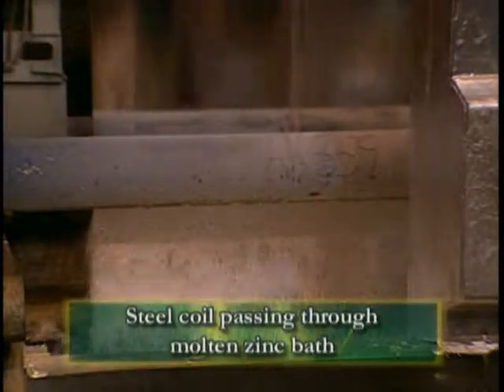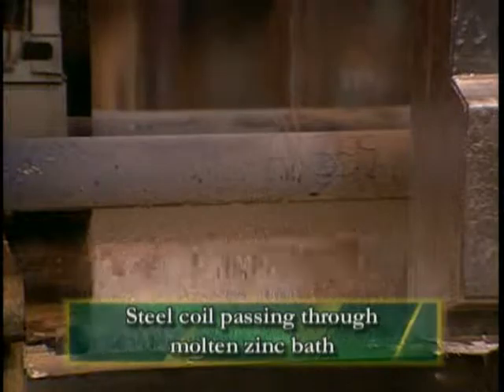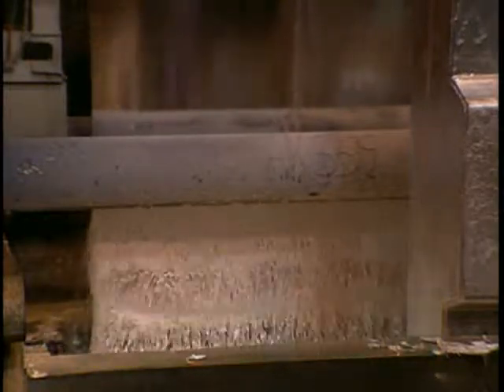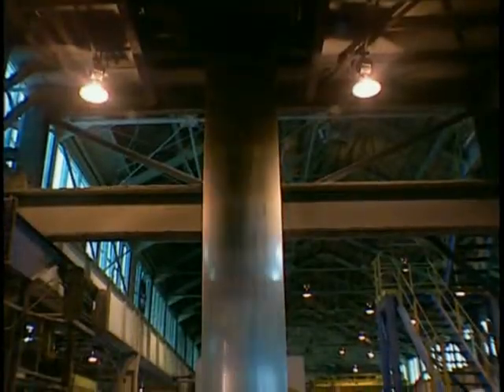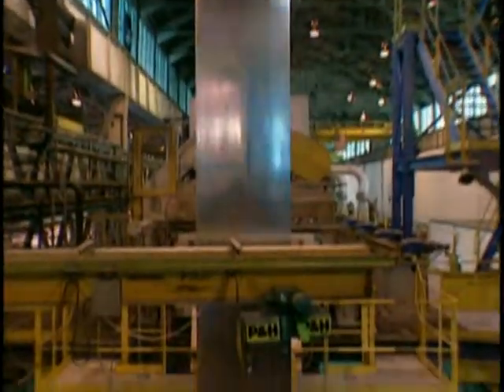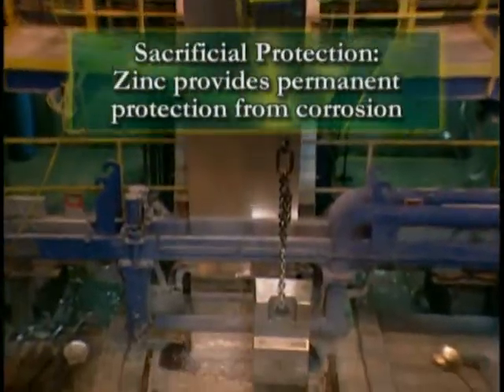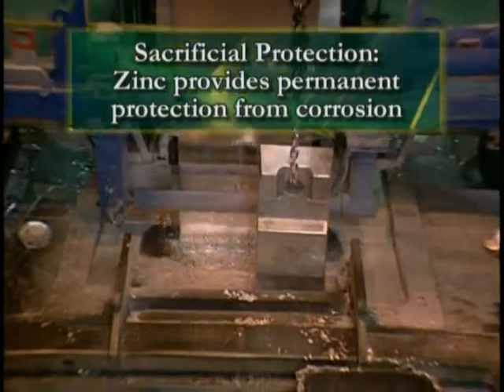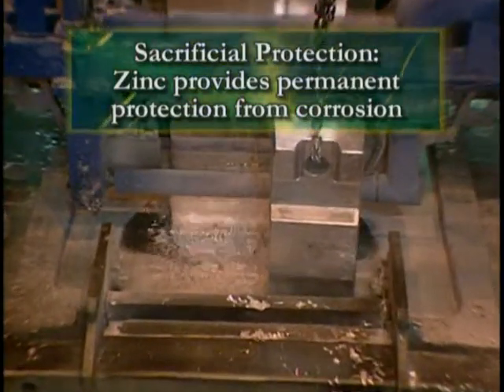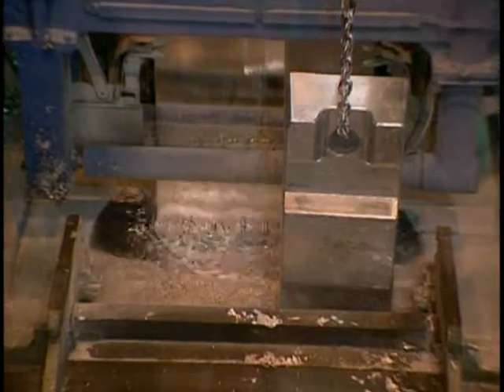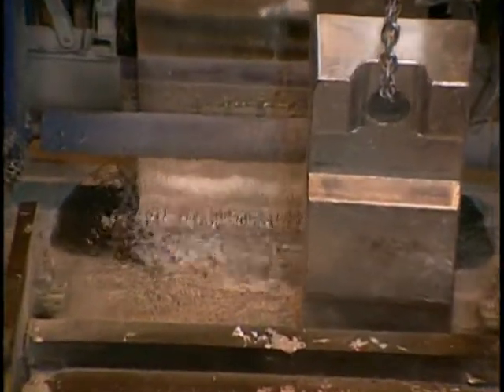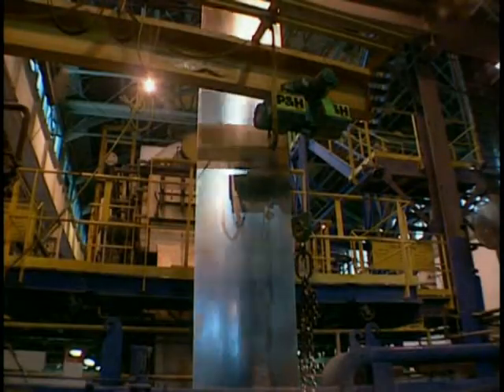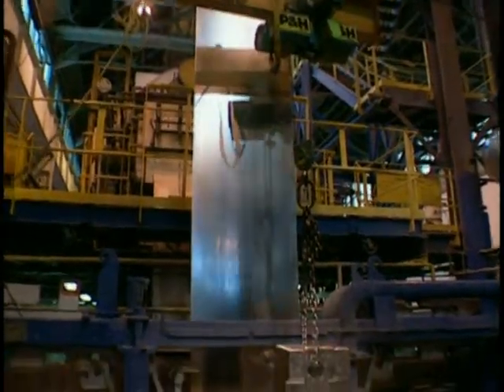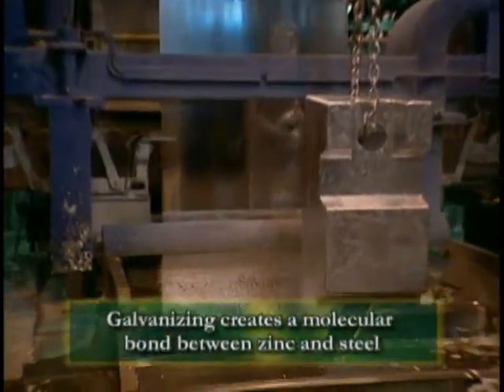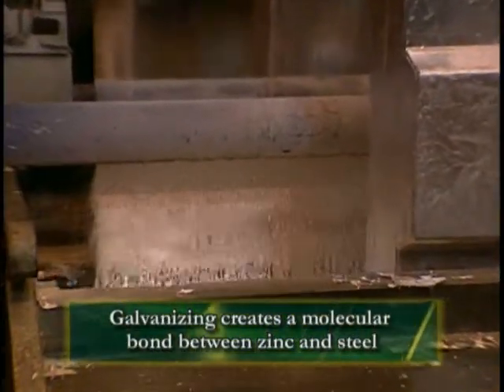All right. Now, why do you use zinc? Well, the zinc provides corrosion resistance, and it does that in two ways, Steve. Number one, it provides a physical barrier, much like a paint does on your house or your car. But more importantly, it provides a sacrificial protection through the theory of dissimilar metals. If you have a cut edge or a scratch where the steel is actually exposed, the zinc will protect that steel from corroding. Right. It's not just a layer that's compressed or anything. It is a metallurgical bond. It's a permanent bond. There's an actual alloy of iron, steel, zinc, permanently holding the zinc to the steel.